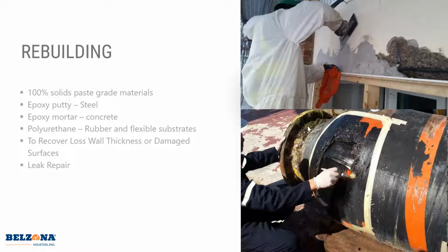The good thing with these products is they can be applied thick. They can rebuild, as you see here. This is a vertical overhead where the rebar is exposed and the concrete's totally eaten up. We can rebuild that. We can do deep pours with our concrete. We have polyurethanes that can be applied 1 to 2 inches thick to repair thick rubber systems like this floating hose. So beyond the steel, which is what we're famous for, there are other substrates we can repair, whether it be concrete, rubber, fiberglass, HDPE. So we've done several different types of